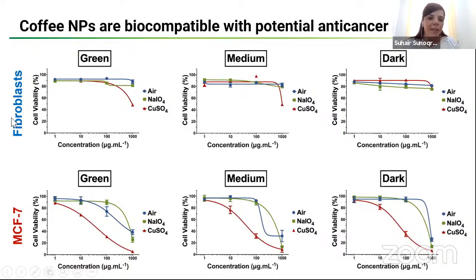And interestingly, we tested their biocompatibility in fibroblasts. They were basically biocompatible to a high degree. But when we tested them on a cancer cell line, the MCF7 breast cancer cells, we noticed they started to show some anti-cancer activity, like they can cause a reduction in cell viability, especially the extracts prepared using copper sulfate. We think the copper ion can contribute to toxicity, but as you can see, it was selective to the cancer cells. So these nanoparticles have a potential anti-cancer activity all by themselves without adding any drug.